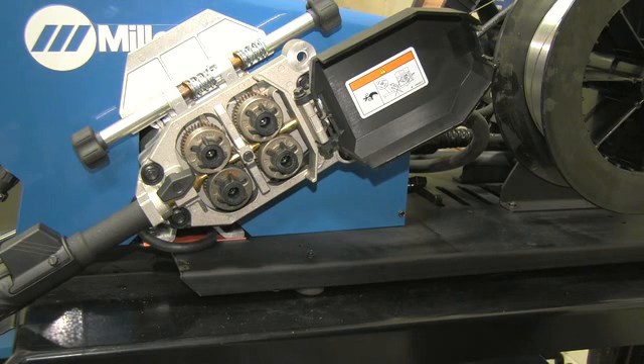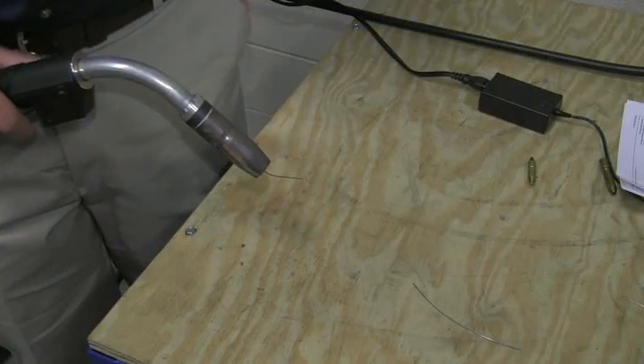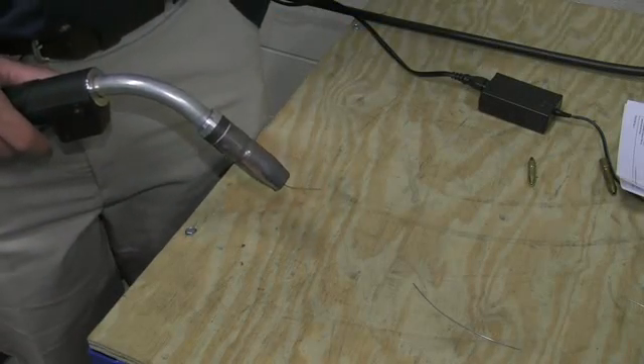And this would be really critical for a smaller wire such as an 030 or 035, because the column strength on those wires is a lot less, and so it doesn't take very much for one of those wires to kink, and then you can get a bird's nest or a burn back at your tip. So another cause of burn back is wire slippage.